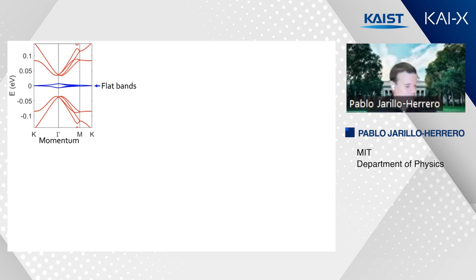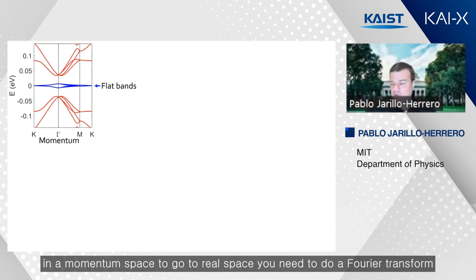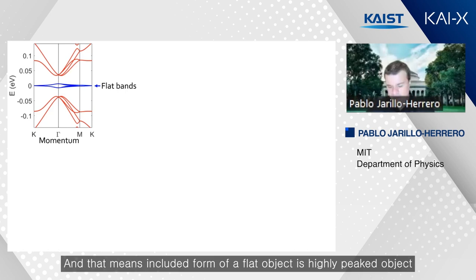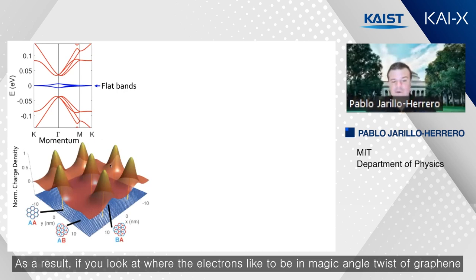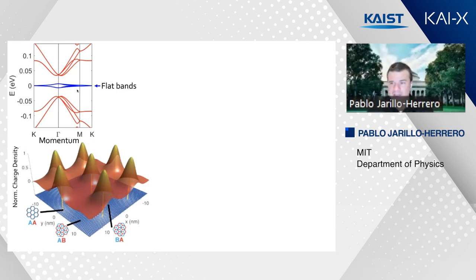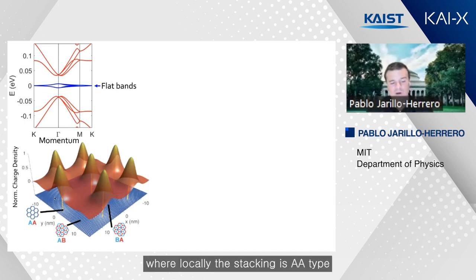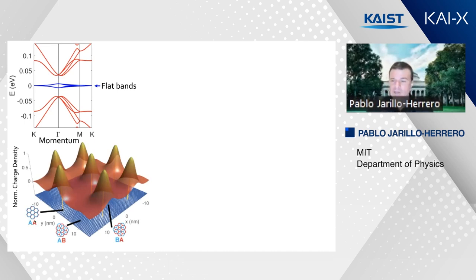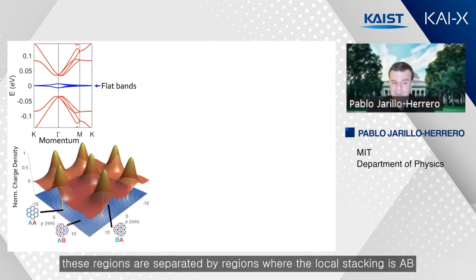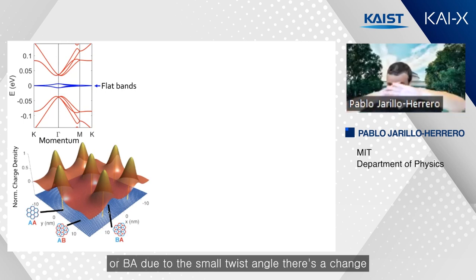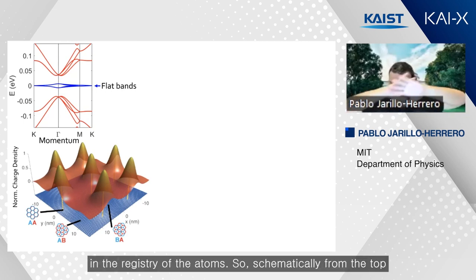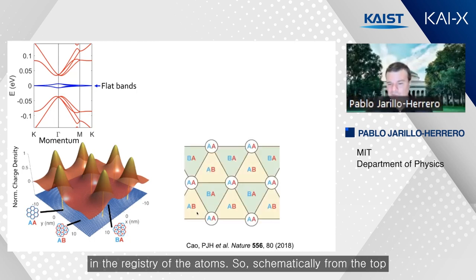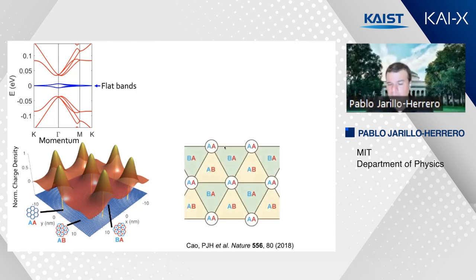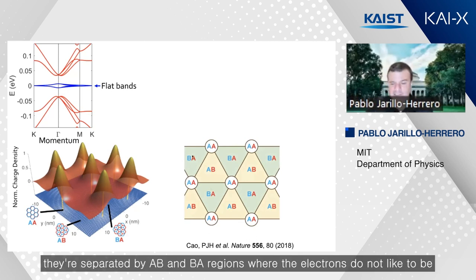So flat band means in momentum space. To go to real space, you need to do a Fourier transform, okay? And that means the Fourier transform of a flat object is a highly peaked object. As a result, if you look at where the electrons like to be in magic angle twisted bilayer graphene, they like to be in regions where locally the stacking is AA type, okay? Now, these regions are separated by regions where the local stacking is AB or BA, due to the small twist angle, there's a change in the registry of the atoms, okay? So schematically from the top, magic angle twisted bilayer graphene looks like this. You have these AA regions where the electrons like to be. They're separated by AB and BA regions where the electrons do not like to be.